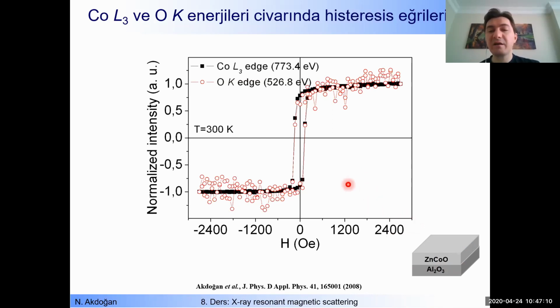Again, the incoming X-ray beam comes in at a certain theta angle and goes to the detector at a certain 2 theta angle, okay? Then we record intensity as a function of magnetic field. What do you see here? We have a magnetic field source, and we increase the magnetic field in the positive direction, then we decrease it, and we increase it in the negative direction.